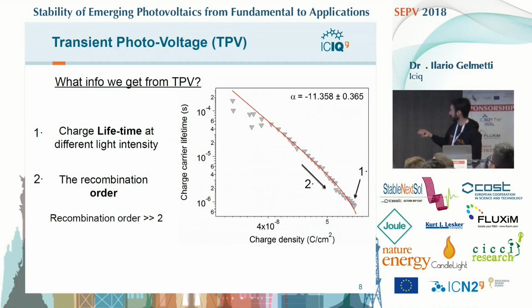Okay, so this is the lifetime of the charges plotted against the amount of charges stored in the device that we obtained from the previous measurement, the charge extraction. From these graphs we can obtain the charge lifetime at different light intensities. For example, the last point will be the one sun intensity. And the recombination order. In perovskite solar cells, the recombination order is still unphysical; in this case it was close to 12. So the correct interpretation is still lagging behind.